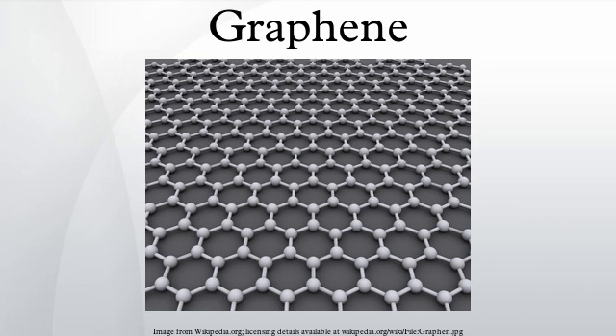Thermal. Graphene is a perfect thermal conductor. Its thermal conductivity was measured recently at room temperature and it is much higher than the value observed in all the other carbon structures such as carbon nanotubes, graphite and diamond. The ballistic thermal conductance of graphene is isotropic, that is, the same in all directions. Graphite, the 3D version of graphene, shows a thermal conductivity about 5 times smaller.